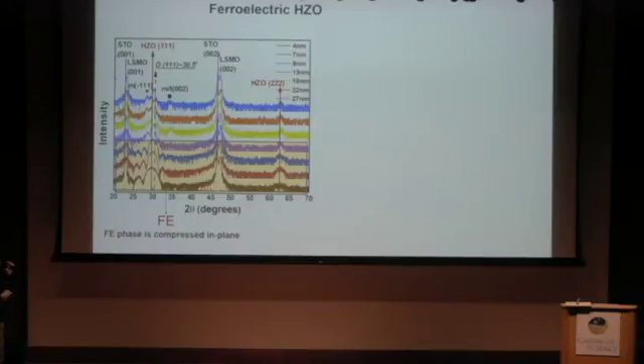And so to understand that, we did structural characterization using both XRD as well as electron microscopy. So here I show theta to theta XRD plots as a function of the film thickness. So this is a busy graph, but I want you to note a couple of things. One is the literature value of the orthorhombic 111 is here. Whereas what we see in films which are boxed here, they are the ferroelectric films. The rest of them are not ferroelectric. So beyond this thickness, it is not ferroelectric.